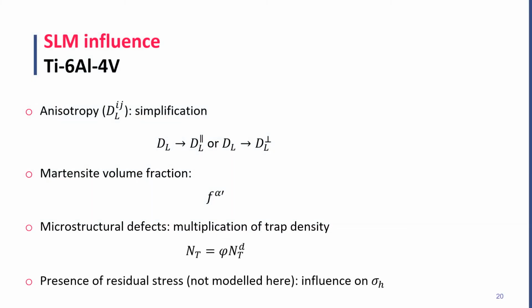We must recall that the context of this study is to predict possible effects of selective laser melting on hydrogen transport and hydrate formation. So we have to consider possible modifications in microstructure and so in the parameters. For example, the building orientation can produce anisotropy. As previously mentioned, we only analyzed two limiting cases. Another input parameter that will surely be increased by the selective laser melting is the fraction of martensite. We can recall that the alpha prime, the martensite, has a lower diffusivity and also a lower solubility than the beta phase. And we also can predict that distortion in the microstructure due to the rapid cooling will also promote a higher number of traps. Finally, residual stresses are not modeled, but of course would influence the process.